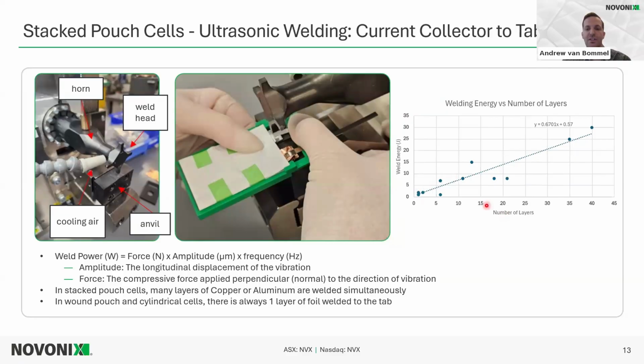And you can see here that these are the weld settings that were selected for a different number of layers. So they were selected by design of experiments, and then selecting a weld energy, and then doing a tear down to ensure that the weld was good. And you notice that when we get to higher number of layers, clearly more weld energy is required.